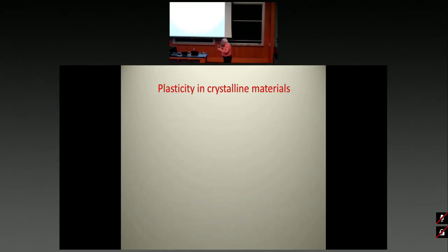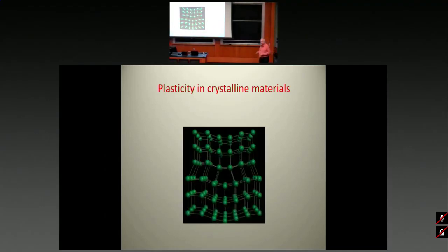So what is plasticity? And first, let me remind you what is plasticity in crystalline materials, because that problem is already understood from the middle of the 20th century, where one of the advances of condensed matter physics, solid-state physics, was understanding that if you have a dislocation in a crystalline material, if you now put a strain, a dislocation will glide. And the glide of the dislocation is an irreversible process, and energy is being used for this, and this is a plastic event. So everything where energy is lost is plasticity. Elasticity is always reversible. You can strain, and if it's purely elastic, you can go back and you gain all the mechanical energy when you go back. Not here. If you have a dislocation, it moves, etc.